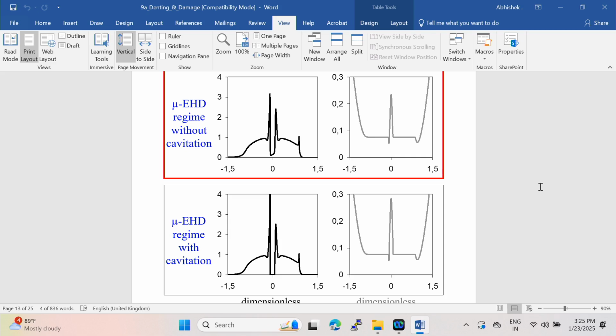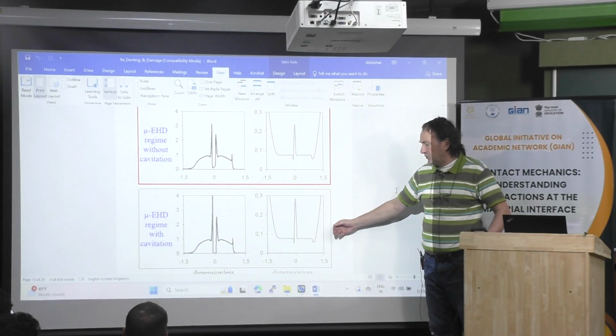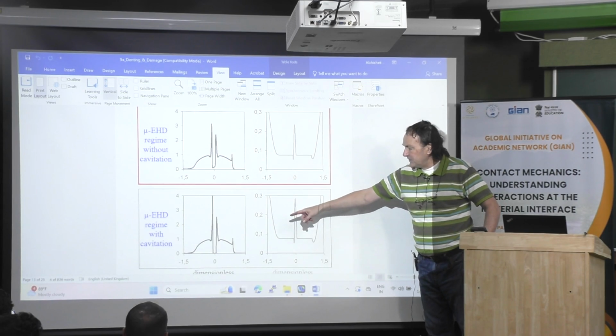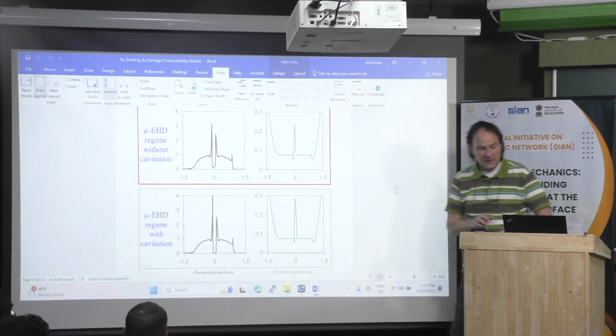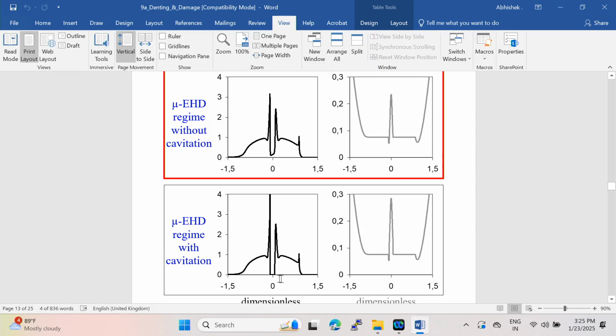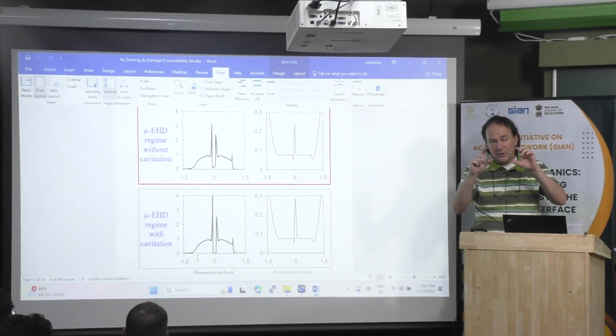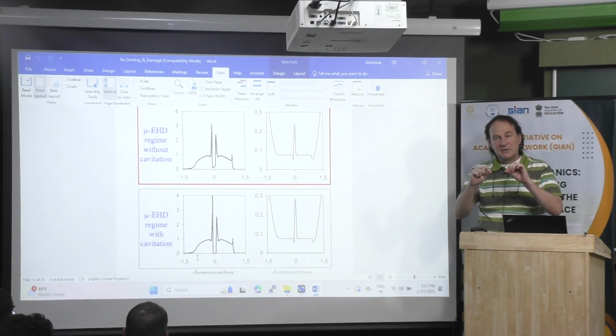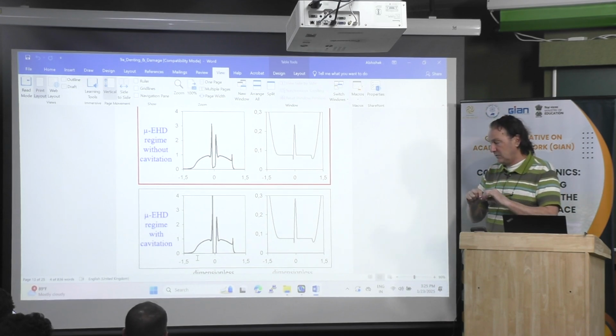Now, if you have a very deep dent, you will have this type of solution. You can see the dent, and you have cavitation in the center of the contact here because there is no pressure. Then there are two points. The first one is that when you cavitate, it means that you may have metallic contact around the dent because you have no lubrication. You have cavitated, then you may have metal-to-metal contact. Then it can be very detrimental for the life of the bearing.